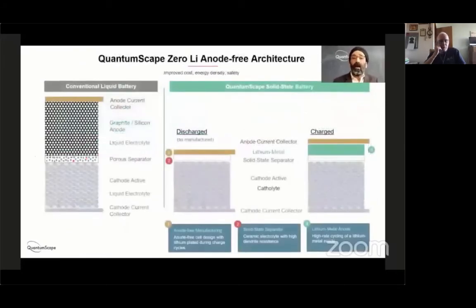So if you could, in fact, make a solid-state separator that was as conductive as a liquid and yet was able to prevent lithium metal dendrites from forming, then you could take the conventional battery architecture shown here on the left, which consists of 3 layers: a cathode layer at the bottom, an anode layer consisting of carbon particles or carbon silicon particles on the top, and a porous polymer separator in the middle. The whole cell is flooded with that liquid electrolyte that I mentioned, which is the medium through which lithium ions are transported.